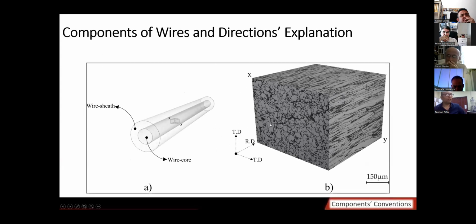These are the components of the wires. The outer component of the wire is known as the wire sheath. The inner component is known as the wire core. This direction is parallel to the rolling direction, and these 2 directions are the transverse directions. Parallel to the rolling direction, you can see that these are iron particles. They are all elongated in the direction of the rolling, and these are transverse images. These iron particles are compressed.